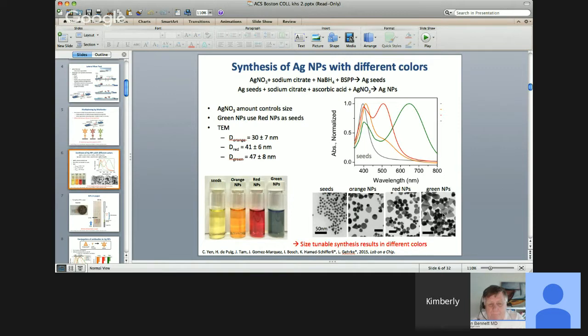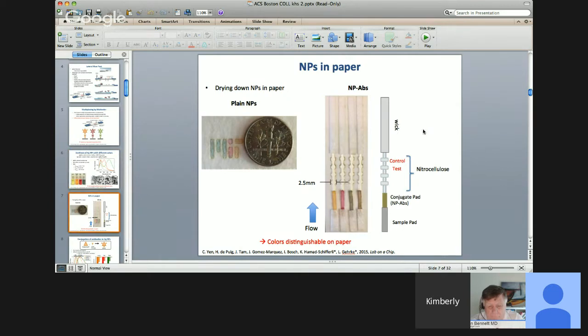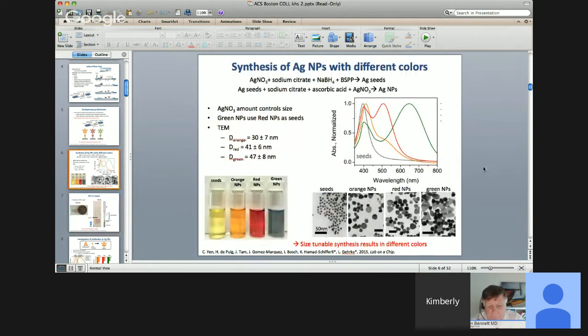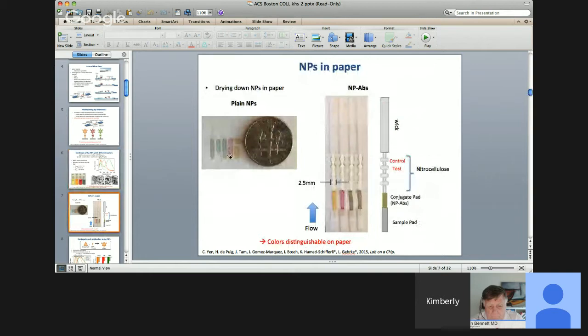So I won't go into the details, but pretty much we synthesized silver nanoparticles that could be made with different colors. It's well known that if you take silver nanoparticles and you change their size, and you can see the TEM image here that they have different sizes, it results in solutions that have different colors. So orange and red and green. And you can see that these are very easily distinguishable by eye. And all we did was just change the synthesis parameters, the concentrations of the reagents, in order to achieve this. Those colors are very easily distinguishable by eye, so we had to also test if they were distinguishable when you put them down on paper.